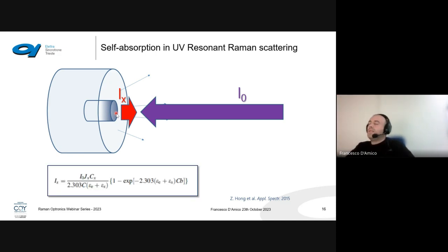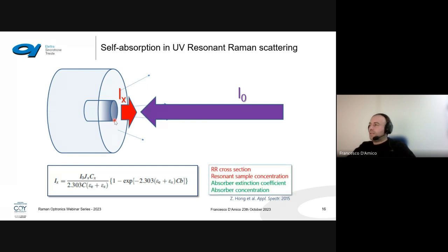What occurs basically is that the intensity of the diffused light in the X direction is due to two effects. When the penetration is high, the whole volume is covered. But in the case that the sample strongly absorbs, only a thin layer is sensitive to the Raman effect.